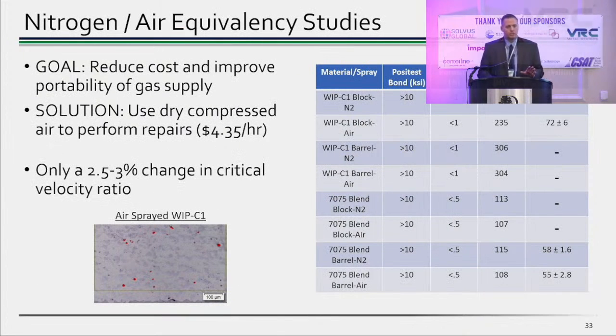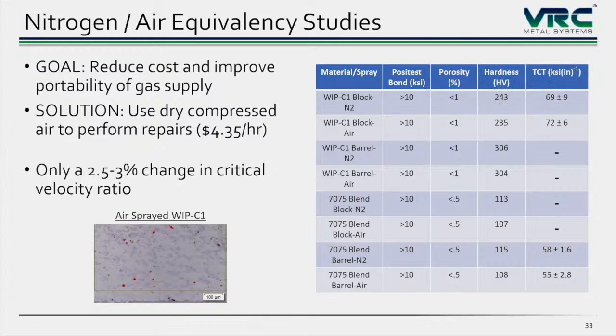All right, so with that, I'm going to switch gears a little bit, and this gets into, as we start to transition to point of need use, can we go from having to generate nitrogen and use nitrogen, can we go to air? So we're looking at that for a couple different materials here. One is the WIP material that Vic talked about earlier, which is a nickel-based blend material. And then the other one is an aluminum blend using 7075 powder. So what you see is in both cases, if we look at posi test adhesion testing, so that's your normal glue failure button, right? And then you look at porosity, you see really no difference between these two.